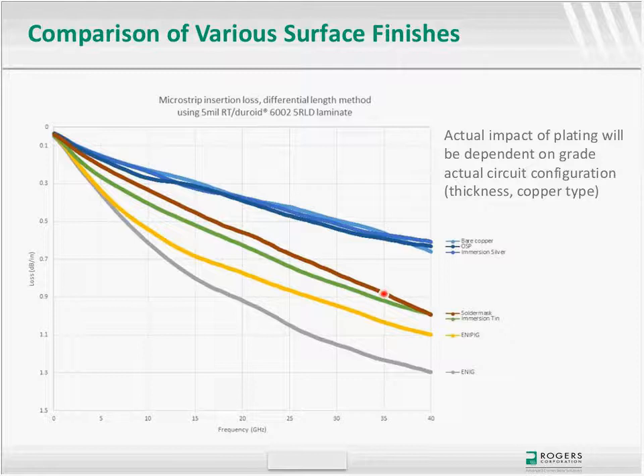So solder mask: we get asked what happens to circuits when you put solder mask on the surface, because some people will do solder mask over bare copper. This is data that we gathered, but in reality, Rogers is going to have to remeasure this value. The dielectric constant that was used in making this circuit took into account how much the effective dielectric constant would change, because you now have a solder mask material on top of the copper, and therefore it changes your effective dielectric constant, because it's no longer just air on top of that circuit. So this was basically a 50 ohm trace, taking that impact into consideration.